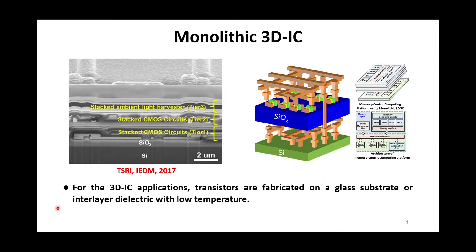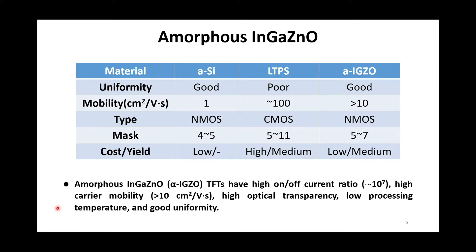It is requested by low fabrication temperature. Therefore, thin-film transistor technology can be introduced to accord with the requirement of the thermal budget. In the previous years, amorphous IGZO become a popular material because of its ultra-low leakage current, higher carrier mobility than amorphous silicon, transparency, low processing temperature, and good uniformity.